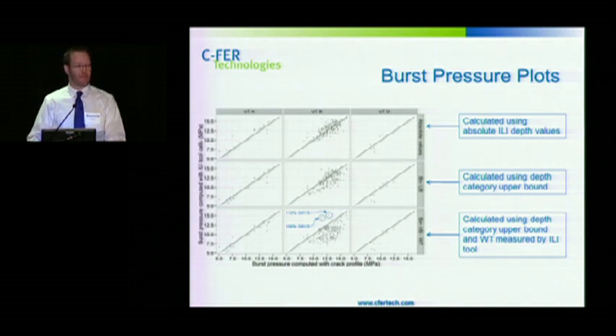Data points that fall below that 45-degree unity line are conservative estimates, meaning that the ILI tool is calling, if you do this calculation, for a lower burst pressure than you would find if you did the same calculation using the field profile. The conservative numbers mean that if you're basing your dig program on this, you're going to find a lot of features that are of a lower burst pressure than you expect just based on the ILI data.